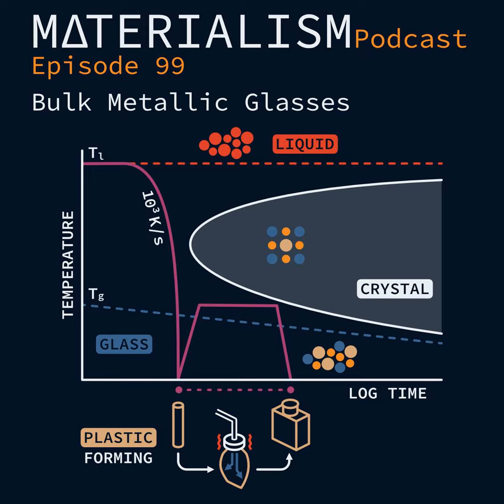So this is the cross-section that experiences the highest stress at first. When you reach the yield strengths of these materials, these very impressive high yield strengths, this is the one that gives in first. In this cross-section, atoms start to rearrange, move around a little bit, and give in to the stress that they experience. The main stress is the shear stress, so that defines the direction. They give in to this stress and rearrange.